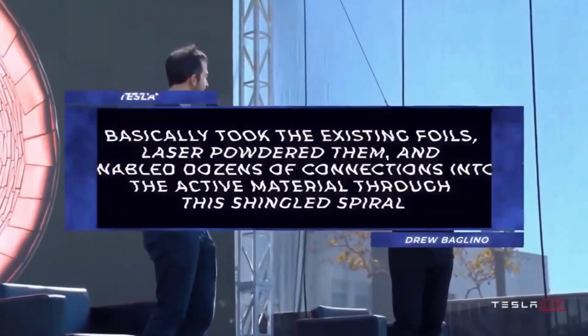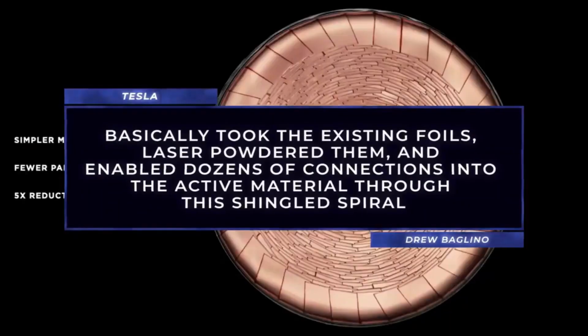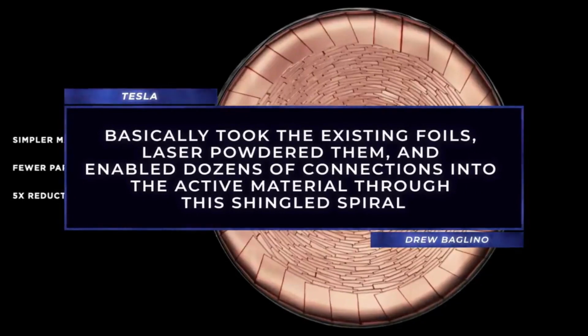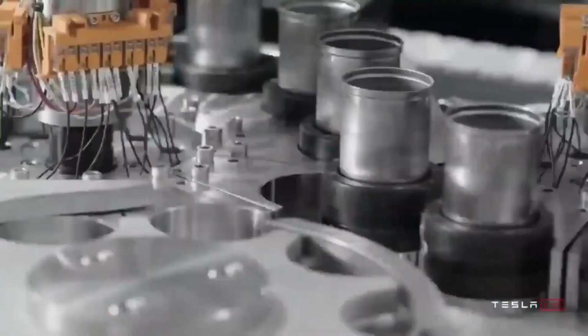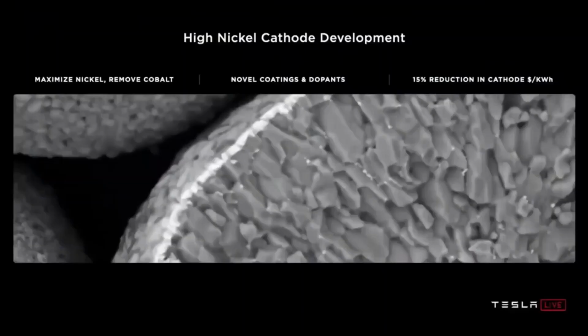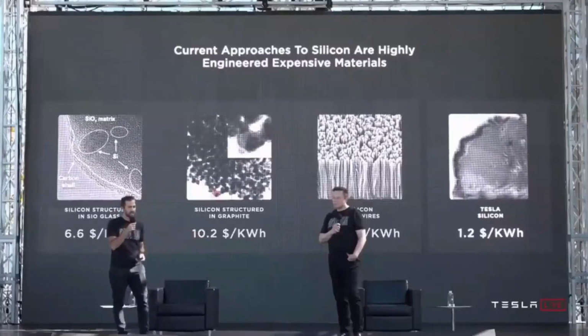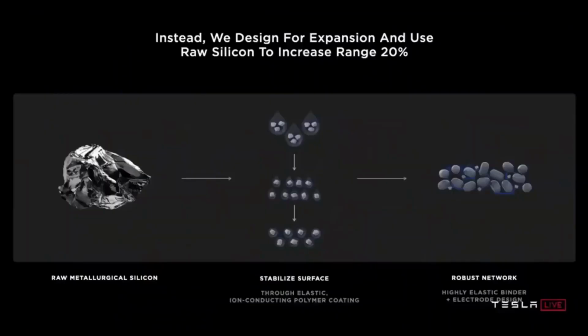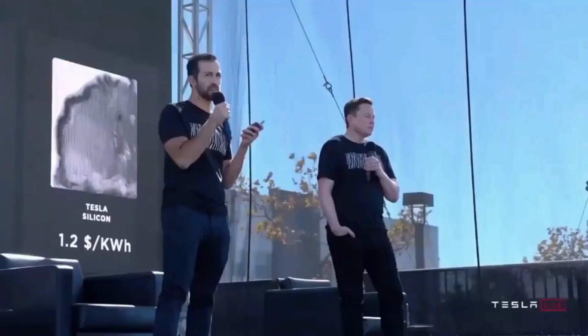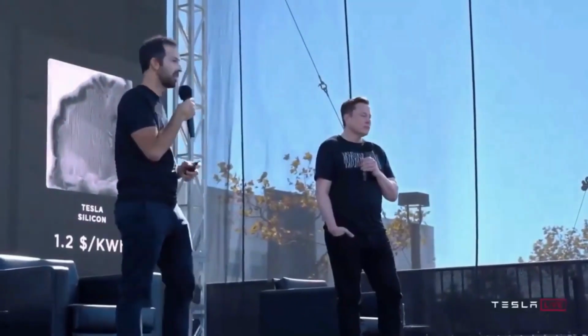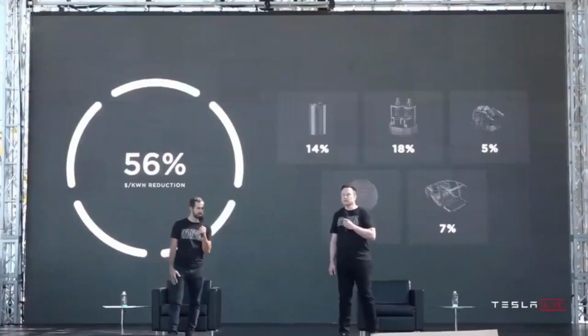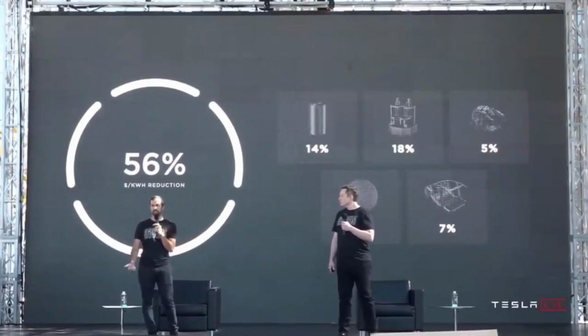Instead, Tesla basically took the existing foils, laser patterned them, and enabled dozens of connections into the active material through this shingled spiral. This more efficient cell design alleviates thermal issues and simplifies the manufacturing process. Tesla also introduced high-nickel cathodes that eliminate the need for cobalt, and improved silicon battery chemistry in which they stabilize the surface with an elastic ion-conducting polymer coating that allows for a higher percentage of cheap commodified silicon to be used in cell manufacture. Altogether, these changes create an expected 56% improvement in Tesla's cost per kilowatt-hour,